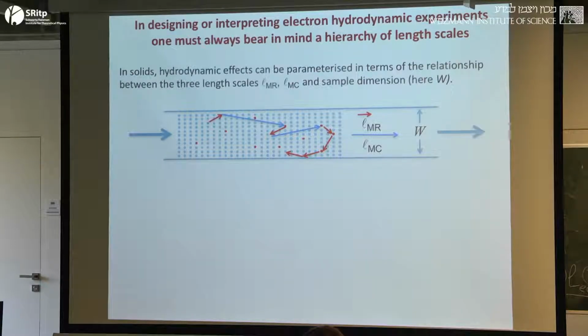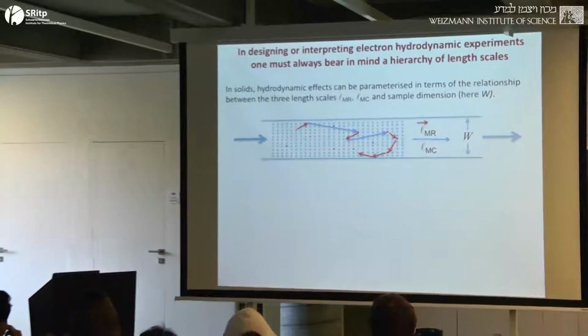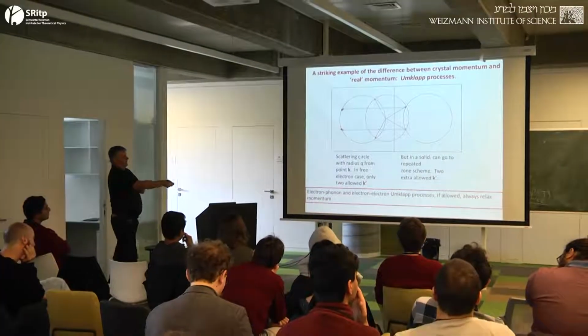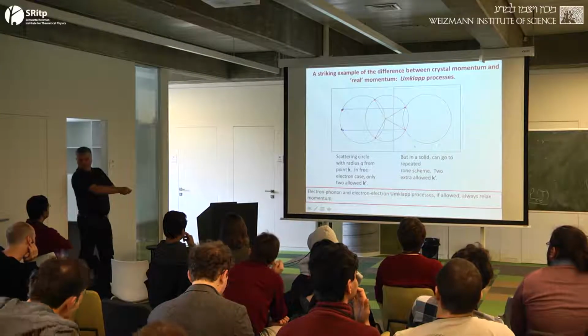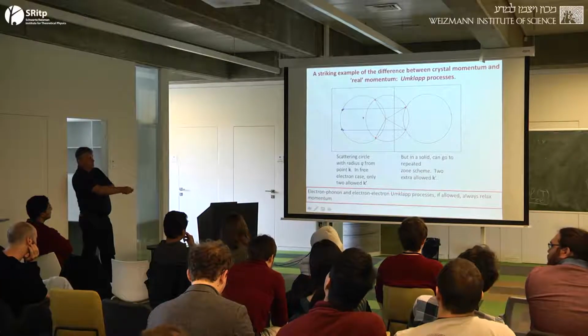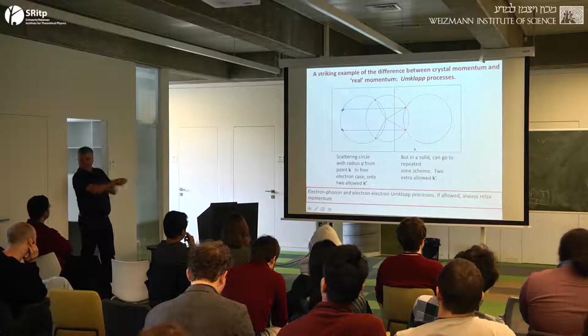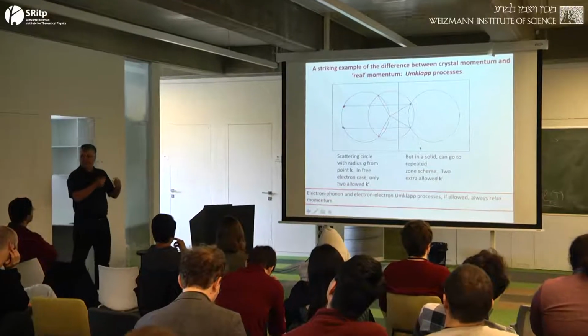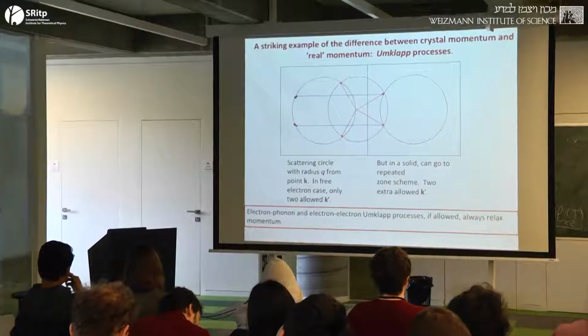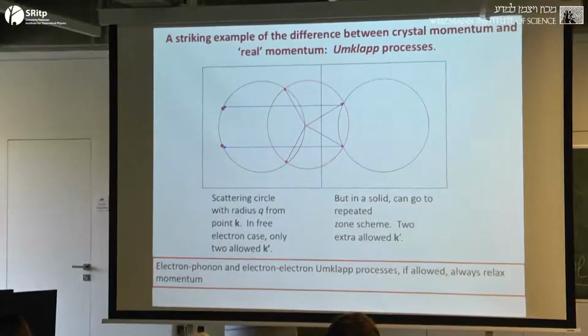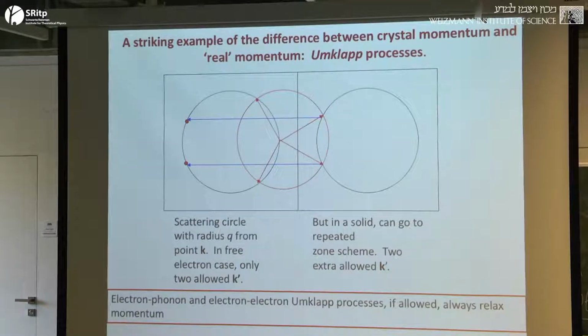So this is for single electron scattering on an impurity, but you can have also 2 electron scattering umklapp. Yeah, you can have 2 electron scattering umklapp indeed, but I carefully didn't talk about the microscopic nature here. If your Fermi surface is small enough, however, even electron-electron processes, 2 electrons, there will be a criterion of size of that Fermi surface below which there will be no more umklapp to worry about. But crudely speaking, there's a total divide here. A low-density system like graphene or a semiconductor 2-deg doped to low doping levels is immune to umklapp. A higher density system like a so-called semi-metal or a metal is not immune to it.